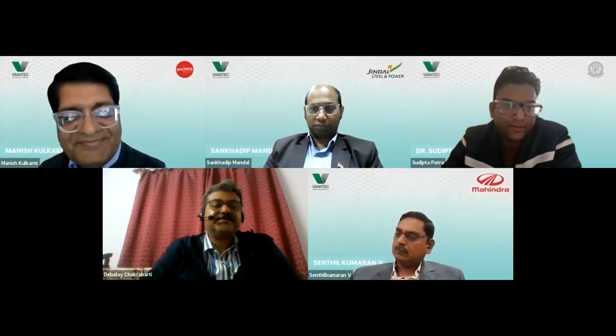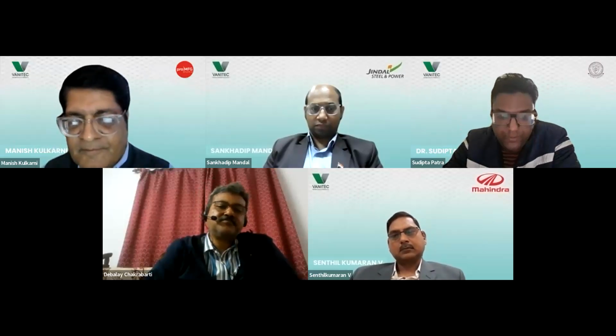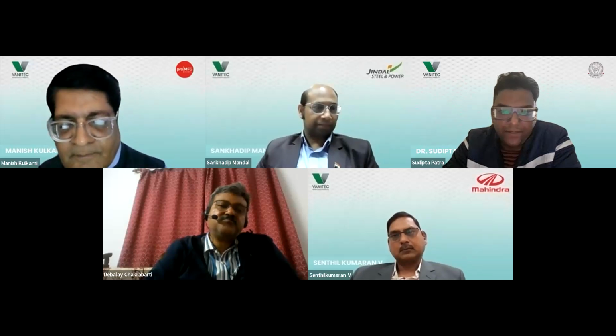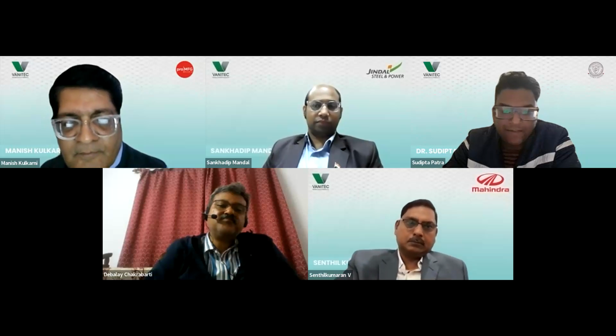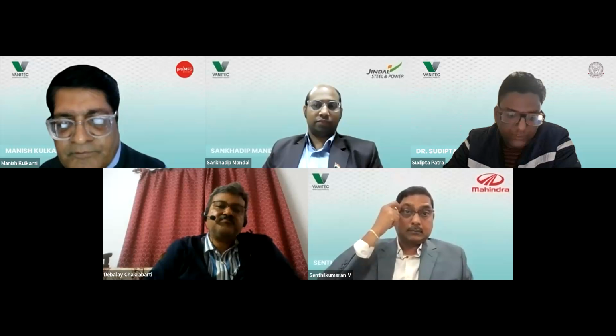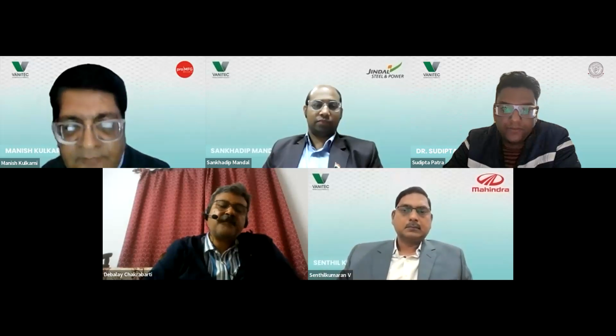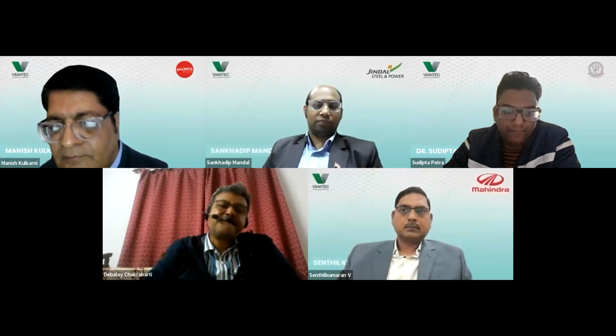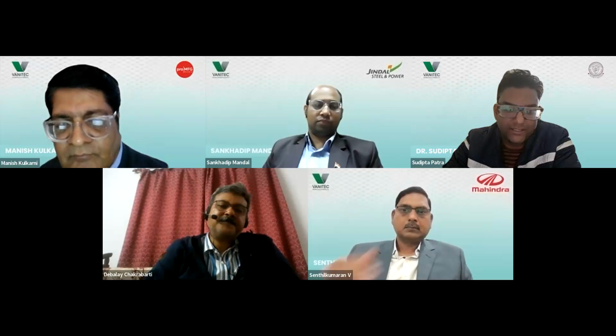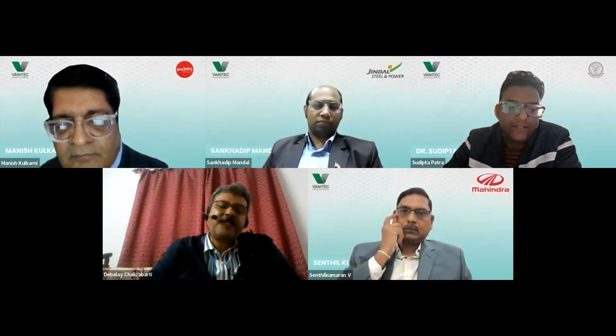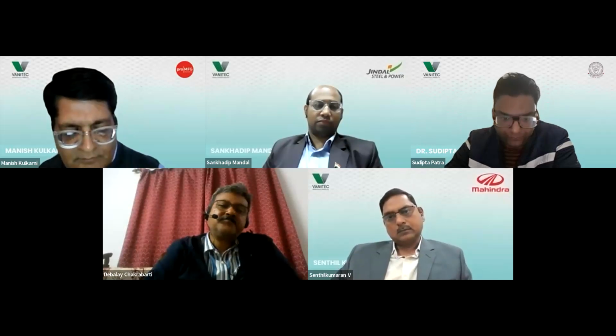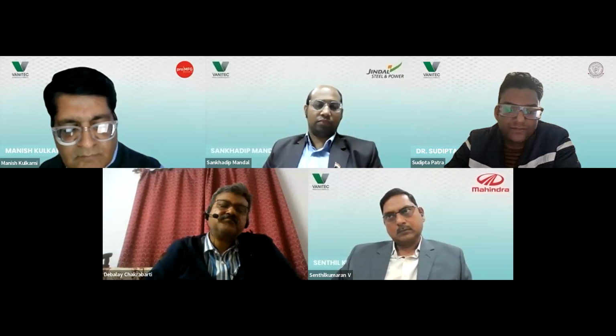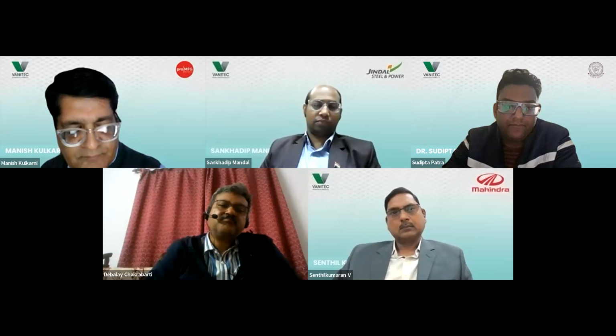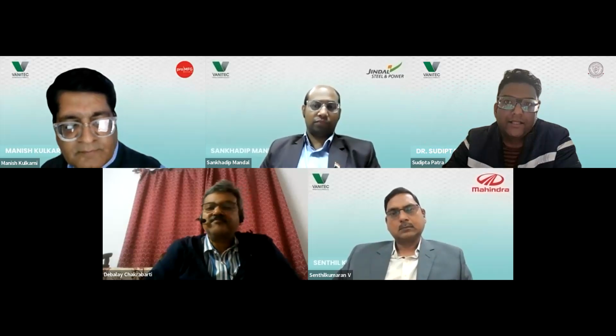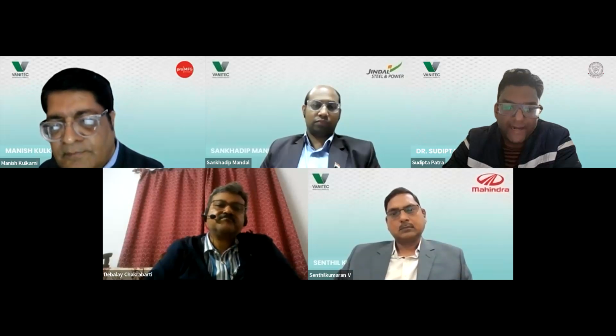Dr. Patra is better to answer. Sudipta: Yeah. Actually, Manishji, normally niobium, titanium, vanadium is added as a stabilizing element in stainless steel. If you add titanium, titanium oxide and titanium nitride form at very high temperature, and titanium oxides are very stable oxides. During steel making, these oxides come to the surface of the slabs, and if we do not grind, at least I think 2-3% grinding is needed overall.